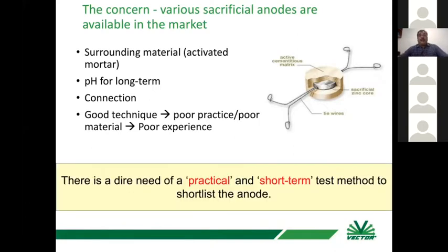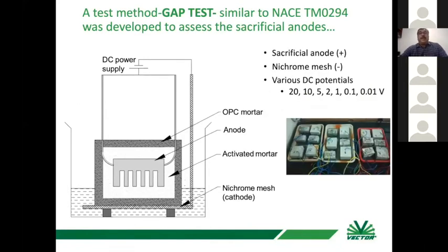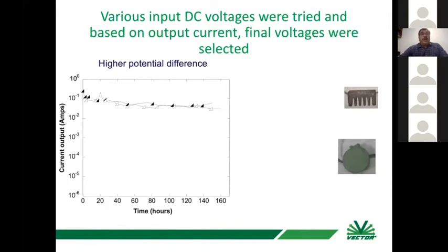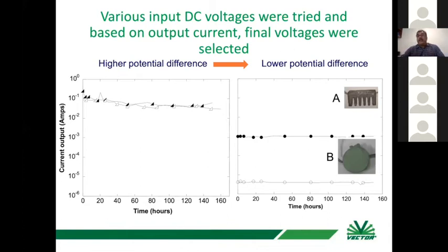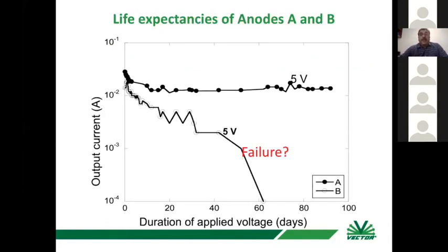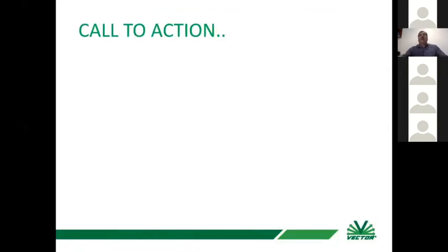For that, one should have a short-term test which can say that this anode is good. IIT has developed such a gap test similar to NACE TM0294, and they developed the test by applying various DC potentials, for very high and low potential differences. They took 2 anodes from the market, and it was found that one anode was failing prematurely in only 60 days. By looking at the anodes, the zinc mass is the same and the anode looks the same, but it fails in 60 days. Another good anode is still performing after 100 days. So you should select a good anode. You should get it tested, and only then use that type of anode, so that the technology is maintained.